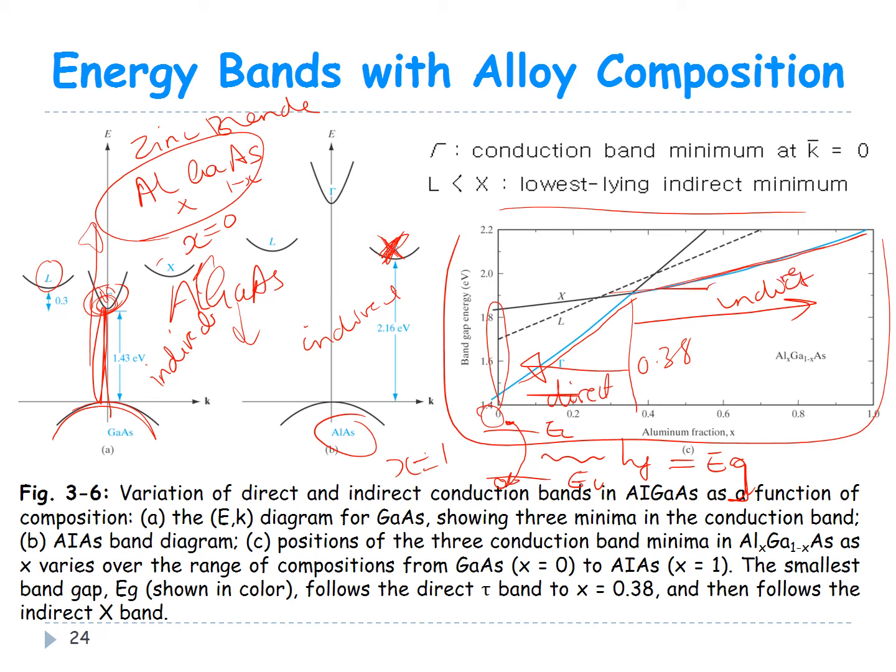semiconductor. So if you want the aluminium gallium arsenide to be used for photoconductive devices, you should make sure that your aluminium fraction is equal or less than 0.38, because that is when the semiconductor is a direct gap semiconductor, where all the recombination processes result in radiation, or you get radiative recombination.